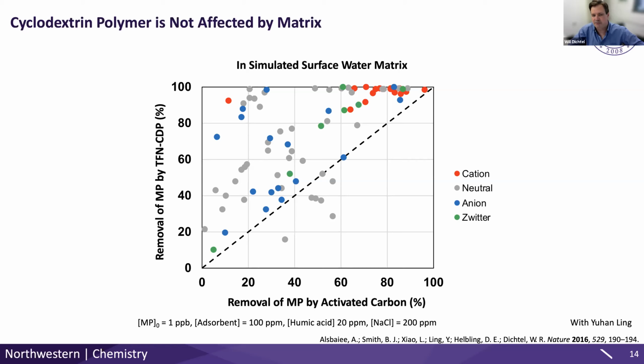And so you look at the trends here, and one just really jumps out: most of the red dots are concentrated very, very highly up to the top of our removal by the cyclodextrin polymer. And that was really unexpected. And it was a really good thing that we tested this many pollutants and got this strong a pattern, because it gave us a lot of hypotheses. It forced us to rationalize what was going on here, and it forced us to understand our polymer a lot better than we did so far.